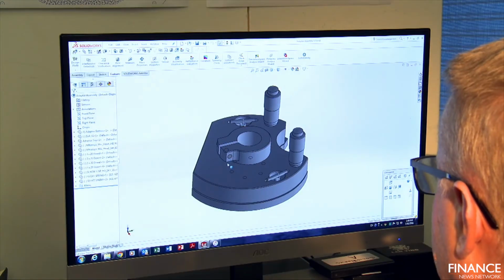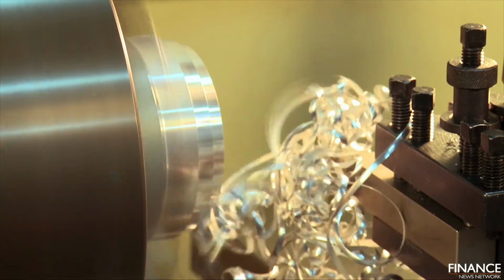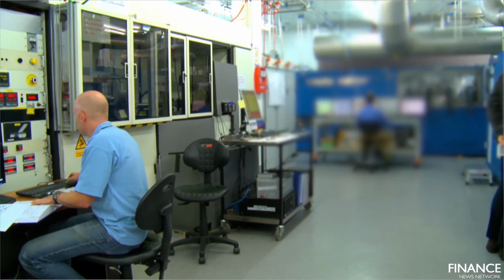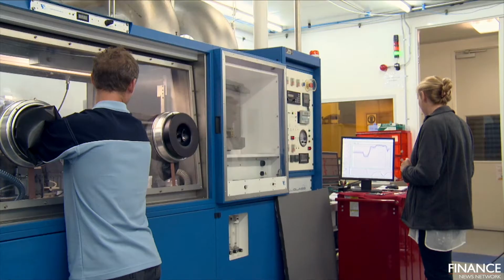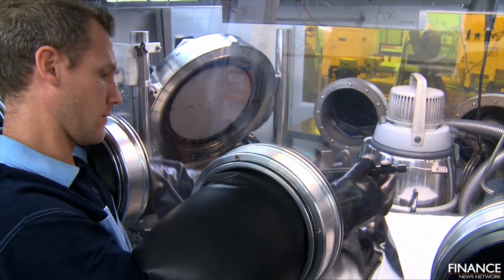Now to the technology and the industry evaluation. Can you remind us what are the competitive advantages of your technology? Yeah, sure, Jessica. Our technology is something that's been developed for a number of years, and the fundamental advantages that we're offering the market are now coming through the stage of being proven up on real industry programs. Essentially, we have a reactor for making this material, gallium nitride, and we do it at a much lower temperature. We use what is called a plasma source. We take pure nitrogen, put it through a plasma, and we get our active nitrogen into the reactor at a much lower temperature than the materials are grown in the current MOCVD process. That lower temperature equates to better quality material.